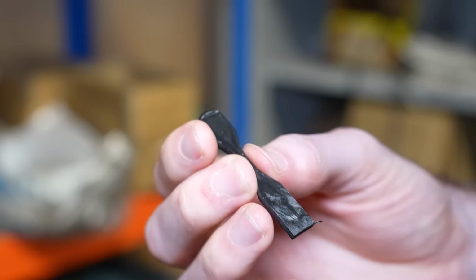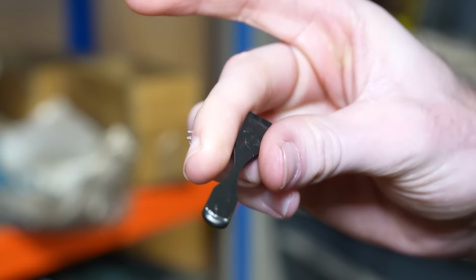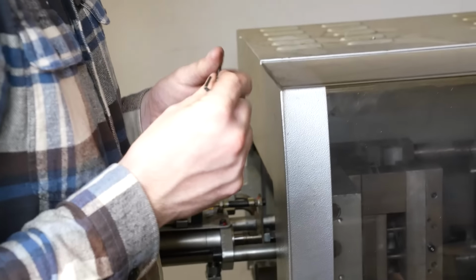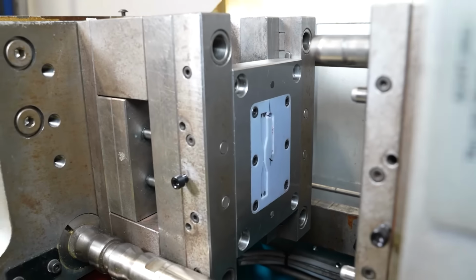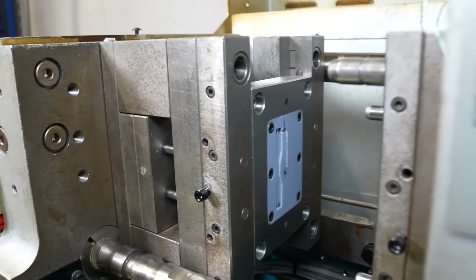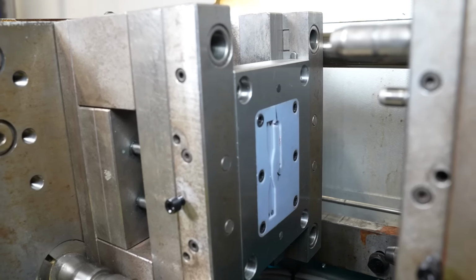During the second round of moulding, a higher temperature plastic which melts at 190 degrees was used. The plastic was well over the maximum temperature limit of the resin material. After a few moulds, the test pieces started to show signs of under extruding, meaning there was a failure in the mould. Unfortunately, there was a small crack in the mould which, due to the high pressure, was forcing plastic out of the cavity, causing an under-extruding failure.